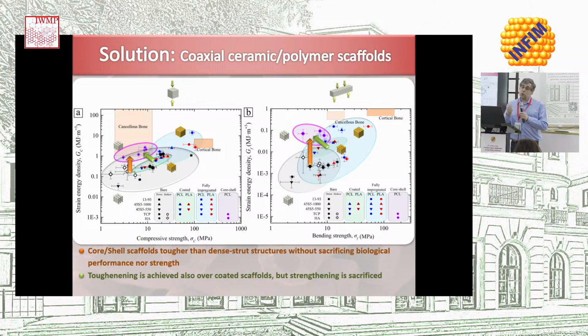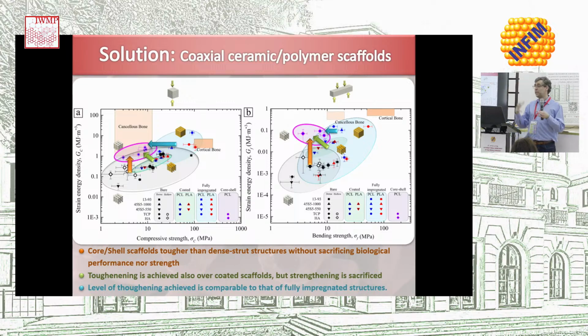Of course, we are losing some of the strengthening that we had when we had the coatings. There is no longer any polymer on the outside, so no defect healing, so the strengthening is lost, but the toughening is better. In fact, the toughening is so good that it's as good as when you completely fill the structure with polymer, even losing the whole macropores. So we are not having the strengthening that we had in that case, but we have the toughness comparable to that of those structures.